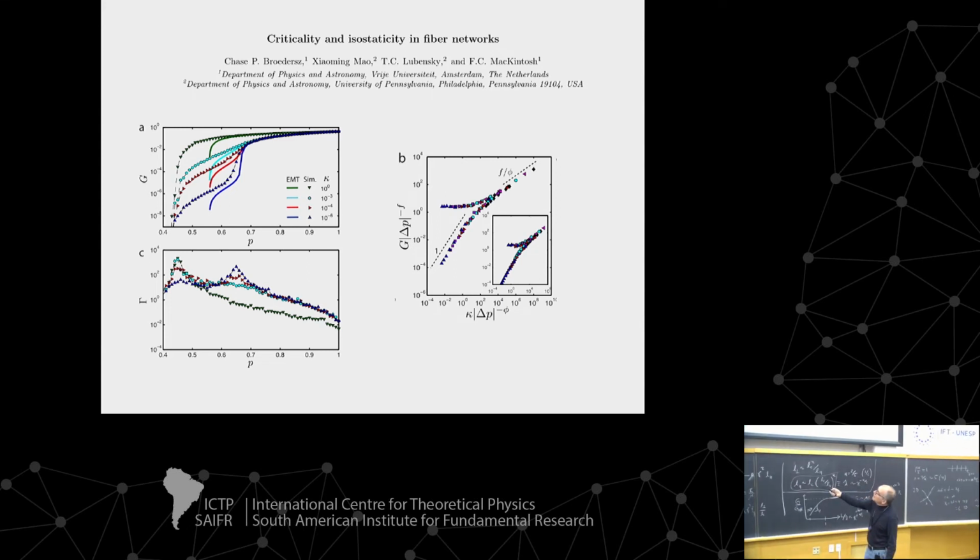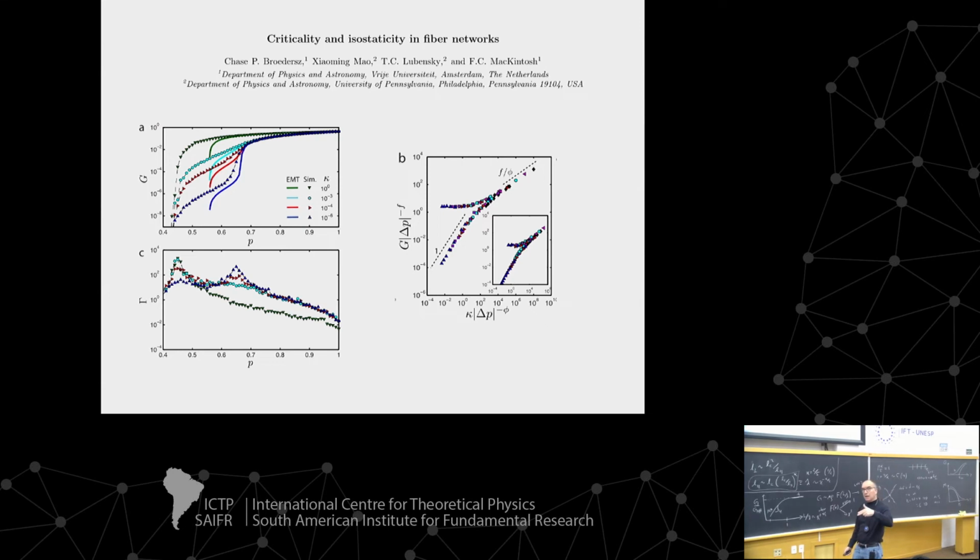And what's interesting is that the bending rigidity has not only stabilized the system, it suppresses fluctuations. The system's no longer critical. We didn't plot it here, but if you were to plot the corresponding curves at kappa equals 0, you'd get something which just crashes right down to 0 there, okay? So just imagine that these curves crash down to 0 at about 0.66. So not only am I getting stability in what would be the floppy phase for the central force picture, but my critical point went away. There's nothing critical. These are just smooth curves.